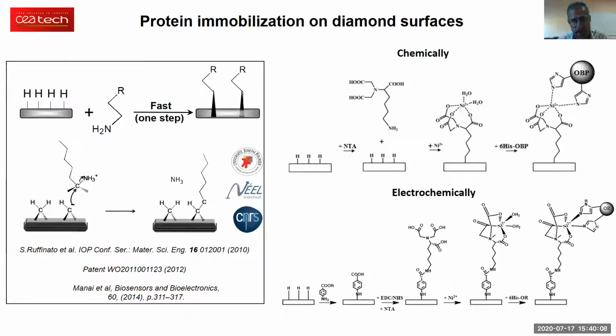So this is a typical example of how we can immobilize a protein on the surface of diamond. If we take, for instance, a native diamond surface that comes out of the reactor, it's hydrogen terminated on the surface. If we expose it to an aliphatic amine, which contains on the other side a receptor, and if we put this system in some proper pH conditions, we are actually protonating the amine group here. We're forming a carbanion on the surface, and through a nucleophilic substitution, we end up with this carbon-carbon bond on the surface. So this is a single-step attachment. It's covalently bonded using a carbon bond on the surface, so it's highly stable.